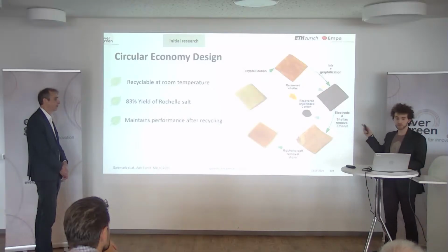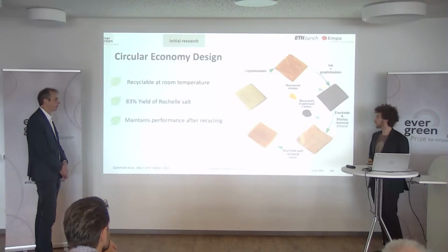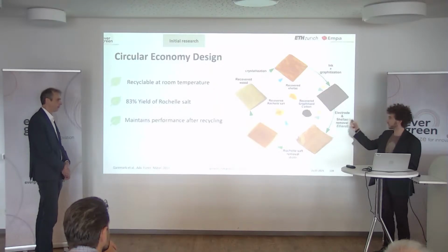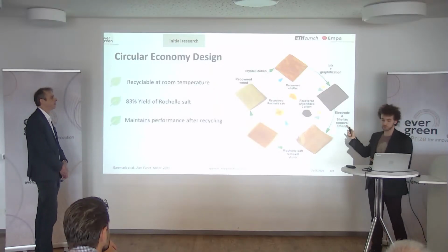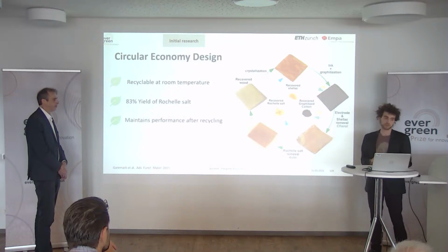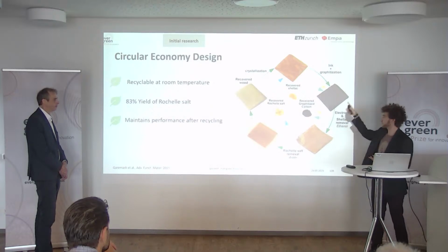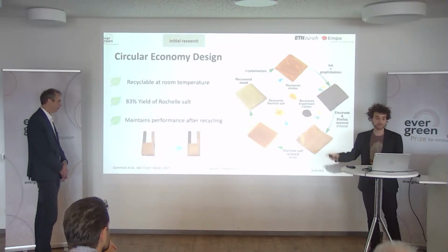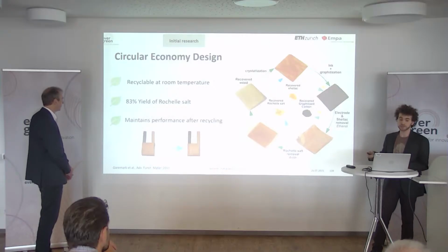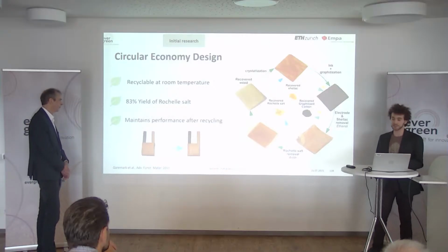Then we removed the Rochelle salt by dissolving it in water, and we're also able to recover these elements, as well as the wood piece, which was also fully recoverable. And we were then able to make a new device. What was most outstanding for us was that we were able to maintain the performance after recycling.